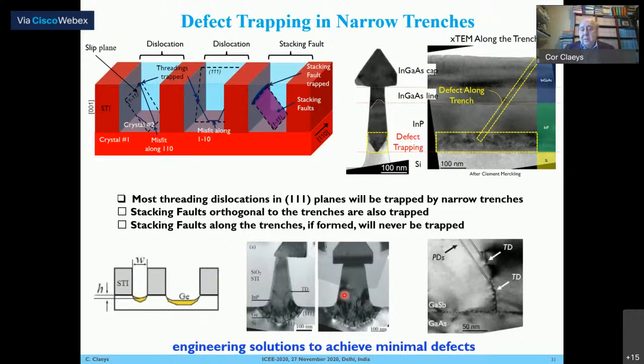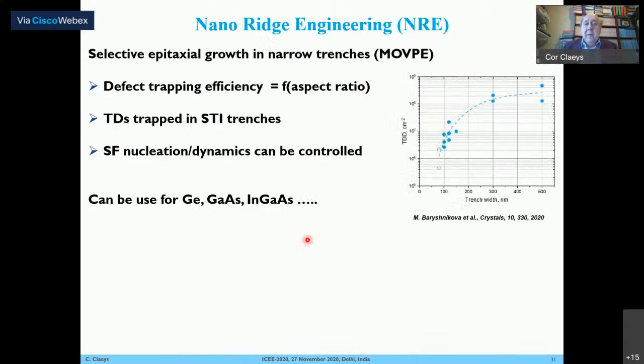And one way is to rely, for instance, on the aspect ratio. Here you see defects in a 200 nanometer wide and a 100 nanometer wide trench. And you see that for the 100 nanometer wide trench, the defects are more located near the interface, meaning that you've got a very nice defect-free region on top. So in order to do nano-ridge engineering, as we call it, you have to rely on the aspect ratio. And here you see in this figure that the defect density is strongly decreasing as the trench width is decreasing. And in general, you can control the threading dislocations. They are not going to cause you a problem. It's more difficult to control the stacking faults. But the nano-ridge engineering approach has been successfully used for germanium, gallium arsenide, indium gallium arsenide, and so on.